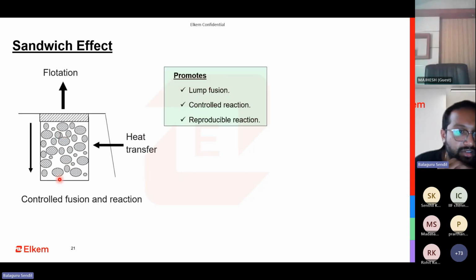So what the sandwich does, basically the correctly designed pocket with the correct size of FSM, will have a lump fusion. All the lumps will fuse and it will start reacting in a certain correct manner. You will have a controlled reaction. You will have a reproducible reaction, the reaction that we saw earlier with magnesium plus sulfur, the rare earth, where we have multiple reactions with FSM.